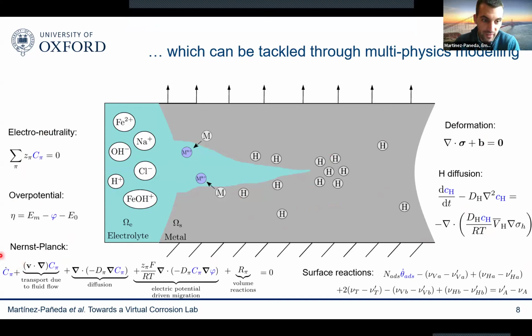So if I look at Nernst-Planck, for example, you can see they have transport due to fluid flow, diffusion, electromigration. And you can see the predictions depend on the diffusion coefficient, Faraday's law, temperature, conductivity of the material. Everything depends on very clear physical parameters. We don't have any magic alpha, beta here that we need to fit to an experiment. All of these are parameters that have a clear physical meaning that we know before we run our simulations. So there's no calibration with experiments. Before I run a simulation for a given material, I know what those numbers must be.